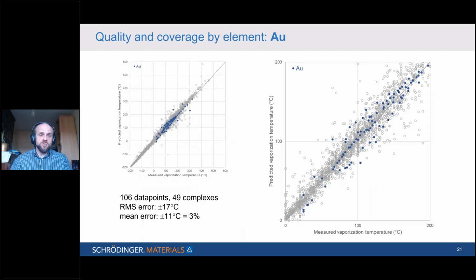Here's an example, gold. These are the gold complexes that we had in the training set. There were 106 data points here, and the error was similar to what I've said before, 11 degrees Celsius or so. And these again are the correlation graphs of the predicted temperature on the y-axis against the experimental temperature on the x-axis. And I just blow up there the area between 0 and 200 Celsius because that's probably the more interesting area for our applications.